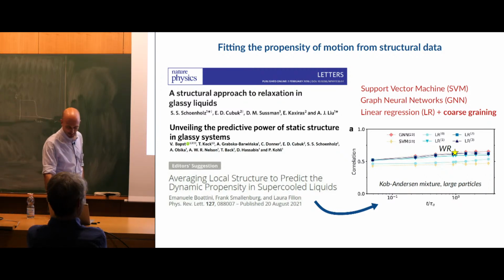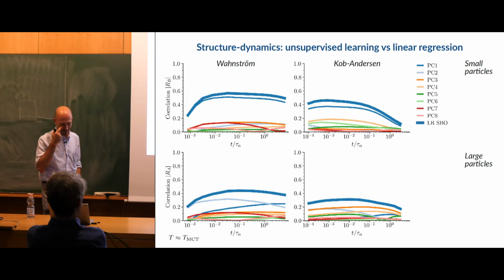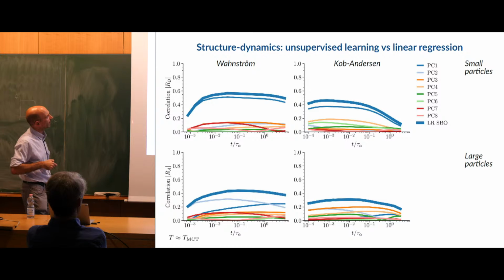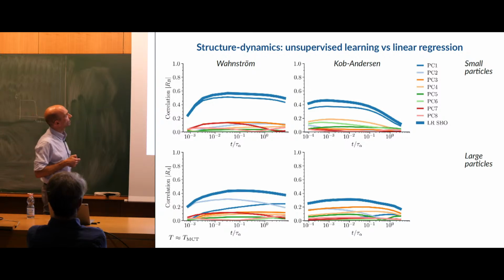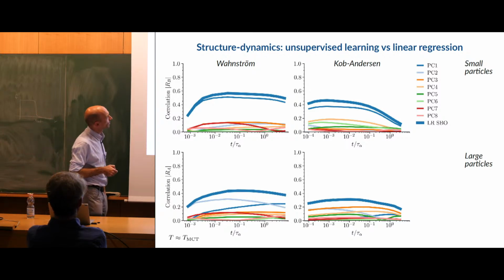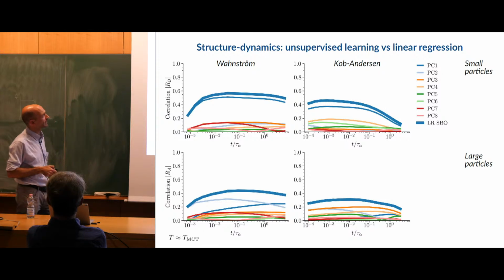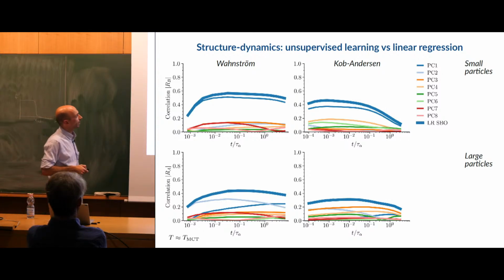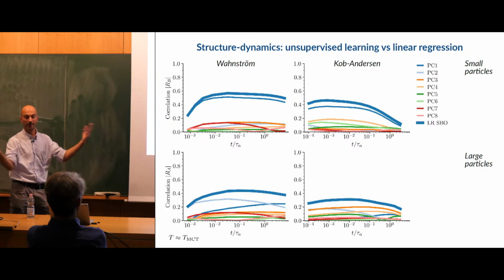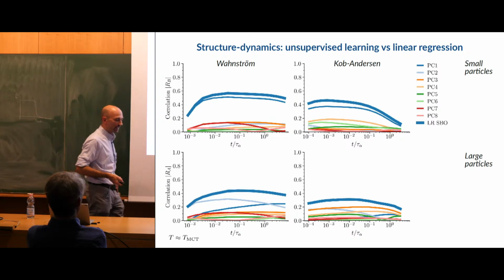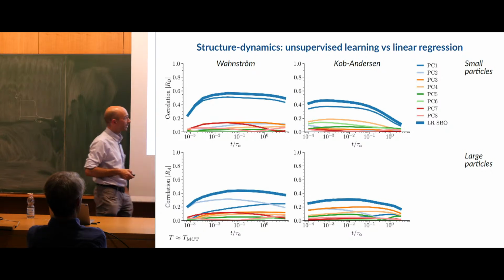Okay, let's see what we can do with our simple unsupervised approach. So here are results separately for small and big particles of these two Lennard-Jones mixtures. I show the correlation coefficient between propensity and each of the principal components as a function of time, scaled by tau alpha. Also, the thick line is a linear regression, as Laura mentioned this morning, to the full descriptor. Okay? So I aggregate everything and try to fit everything with linear regression.